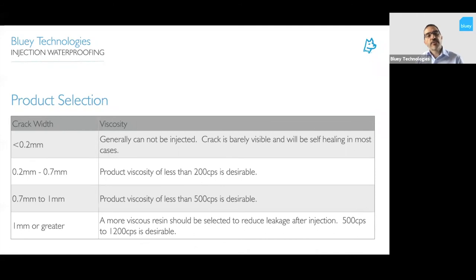And then the crack width, just to look at that in a little bit more detail. A crack of less than about 0.2 millimeters is very difficult to inject. It usually requires a very low viscosity resin and extremely high pressure. The crack is barely visible anyway, and in most cases would be self-healing. And as we said, up to 0.3, it's going to protect the steel anyway. So why are we injecting it is the question. So typically below 0.2, we won't go looking to inject that type of crack.